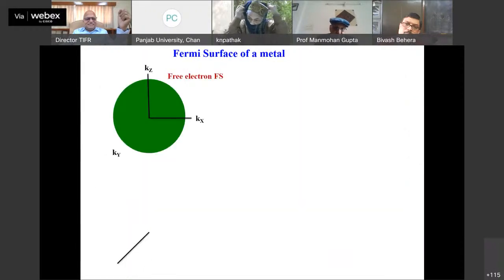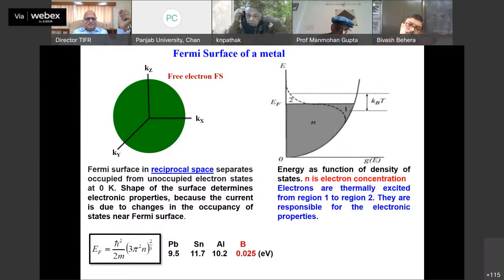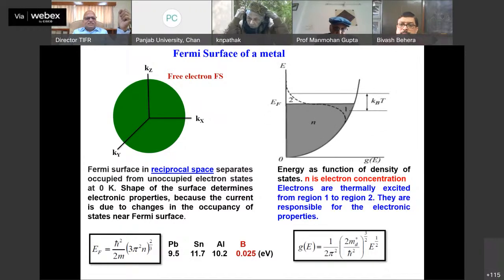So let me just give a simple introduction to the solid state physics, which you know. We know that in metals, at least at absolute zero, all the energy up to EF is filled and the rest is empty. And this Fermi energy is given in terms of Planck's constant, the mass, and also the number density of the carrier concentration. The typical values are, for lead, 9.5, and it goes to 10.2 electron volt for aluminum. And for bismuth, you see it's 25 milli-electron volt.